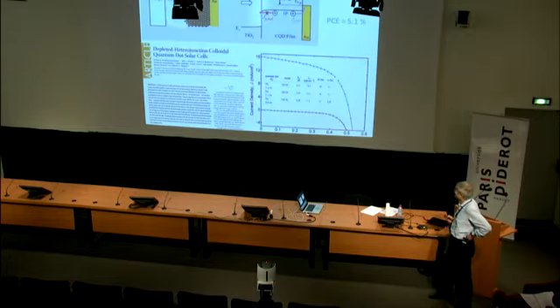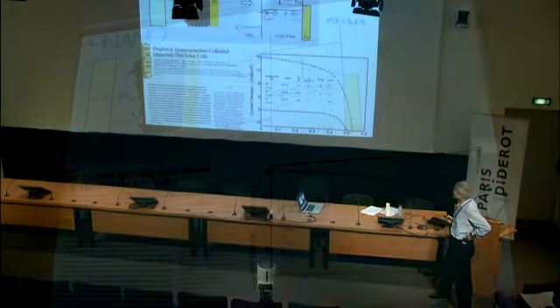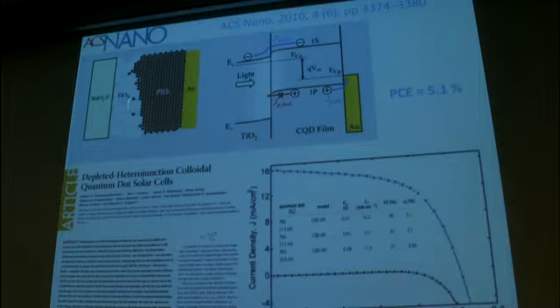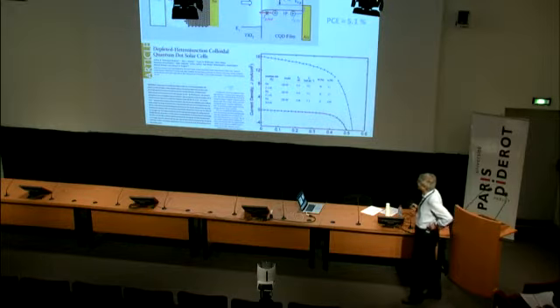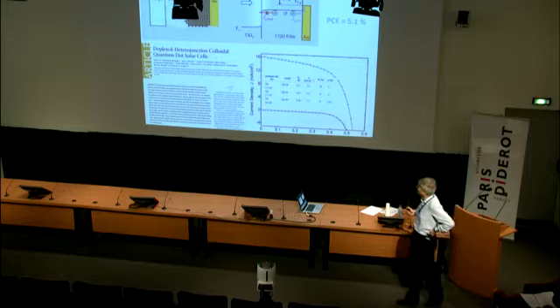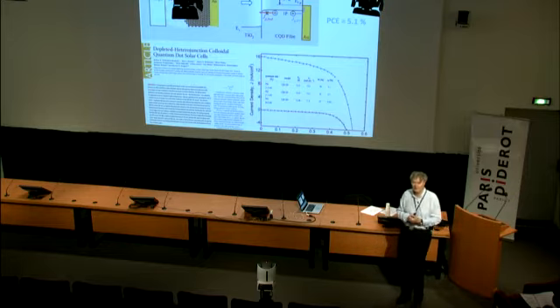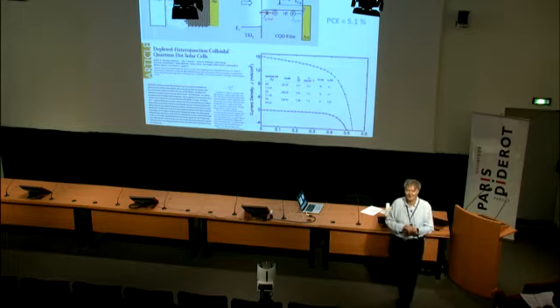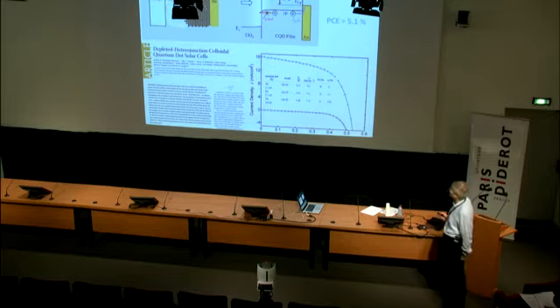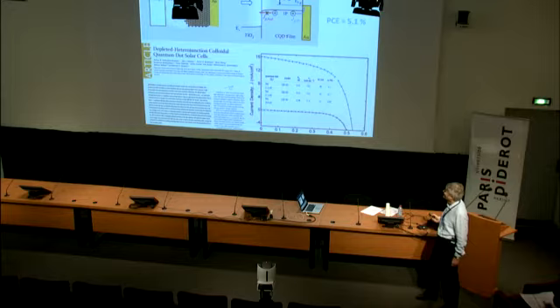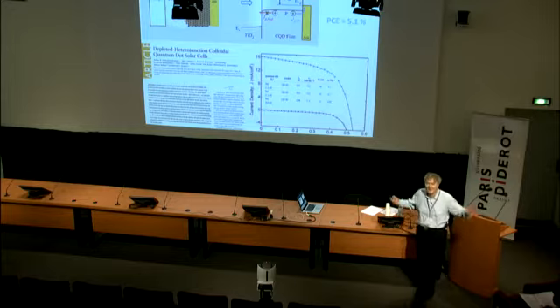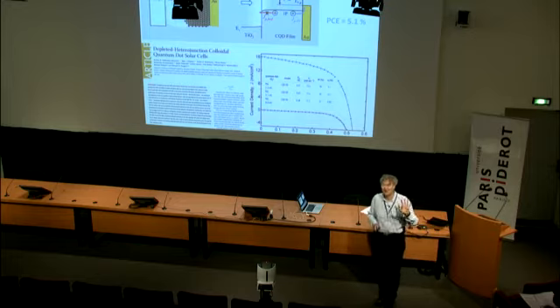There are also others, I would say cousins now, that emerged that actually don't use electrolytes anymore. These are just quantum dot sensitized films. And it's amazing that we can get up to 20 milliamps per square centimeter. Here's something that I thought would never be possible. Actually, I went against my own convictions that this system could work, because here the lead sulfide assumes two roles. It absorbs the light and injects carriers, but it also is a hole conductor. So one should never be dogmatic.